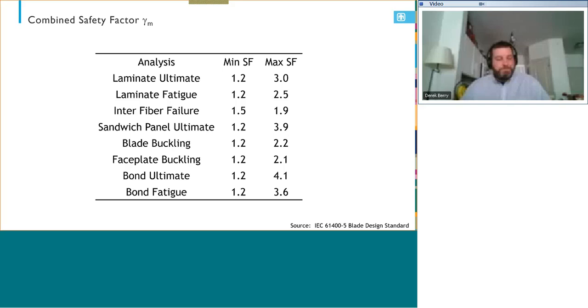For wind blades, they're bonded together with adhesives. We often have problems with some of the adhesives at what we call the trailing edge or the back of the blade coming apart. And in some cases, that is because the blade was designed for a certain mode of crack growth, something like shearing. And what ends up happening, because of deflections of the cross-sectional shape, we end up with peeling stresses. And so we can end up with a design that is locally inadequate, just based on not doing the correct analysis, or in some cases, some part of a blade failing and then causing problems with another area. But you can see here, you can get quite low safety factors. I would say 1.2. If you're able to really well characterize your structure and your material, it can be quite a bit higher if you don't.